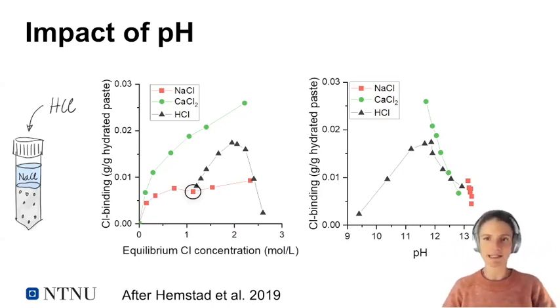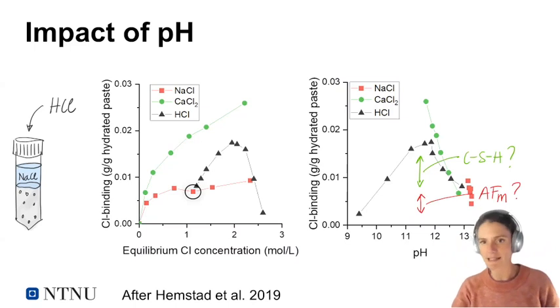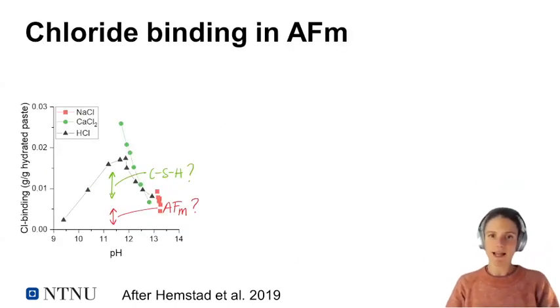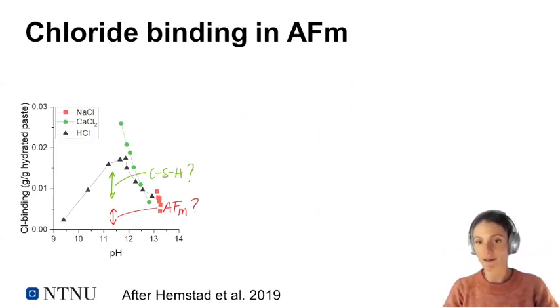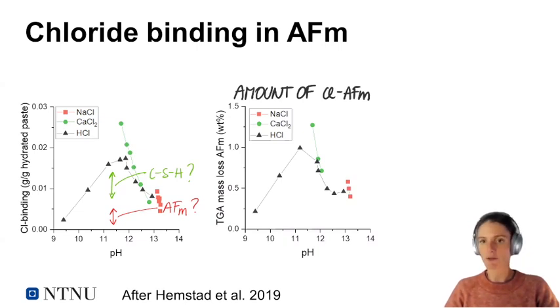But then we also wanted to link this to our binding phases in our cement paste. So what's the role of CSH? What's the role of AFm or Friedel salt in this? This is work done by Peter Hemstad during his master thesis and the beginning of his PhD, together with Alisa Machner. What Peter did is he quantified the amount of chloride AFm using TGA, and he plotted this as a function of the pH.